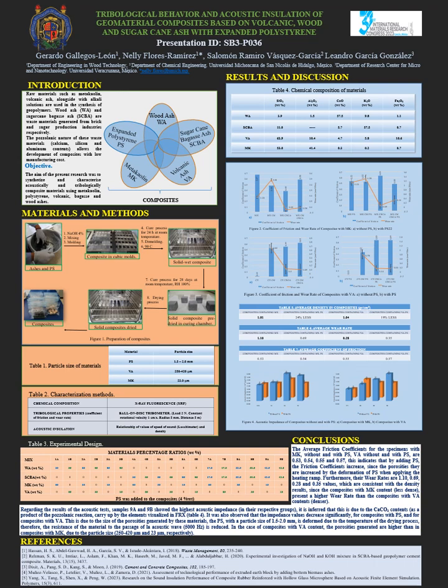The average coefficients of friction for the specimens with metakaolin without and with polystyrene, volcanic ash without and with polystyrene are 0.53, 0.54, 0.55, and 0.57. This indicates that adding polystyrene increases the coefficient of friction, since the porosity is increased by the formation of polystyrene when applying the heating ramp.